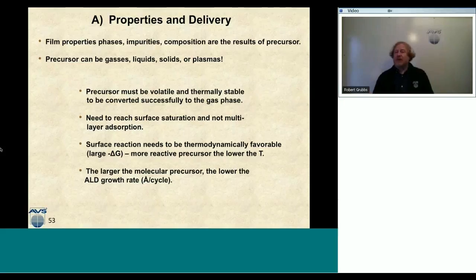The film properties, the impurities, and the compositions are all a result of what precursor you choose. Precursors can be gases, liquids, solids, or plasmas. It's neat that we're using all four states of matter just for chemical precursors in ALD. I'm not sure that any other deposition technique possibly uses all different forms of matter. The precursor must be volatile to get into the gas phase, and it also has to be thermally stable to get the vapor pressure up if we need to, to get it into the reactor and then react on our substrate surface. We need it to reach surface saturation and not multi-layer adsorption. We don't want the ALD precursor to react with itself at higher temperatures. Maybe that compound is stable at low temperatures, but as soon as it hits a hot substrate, it has a surface reaction that makes it react with itself.